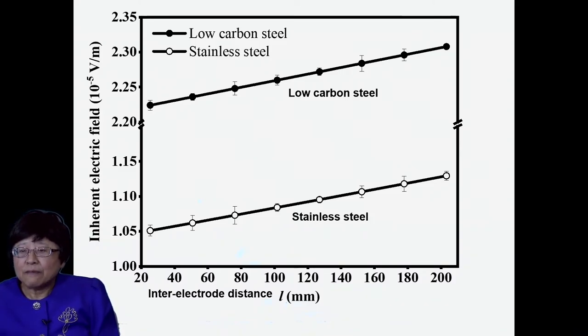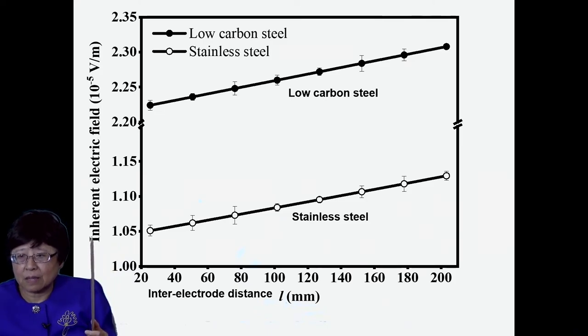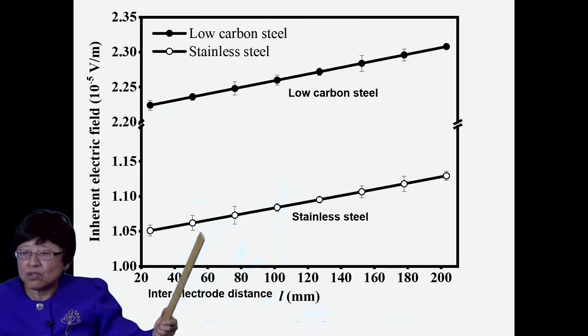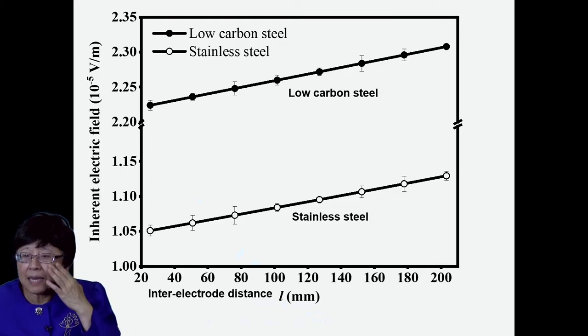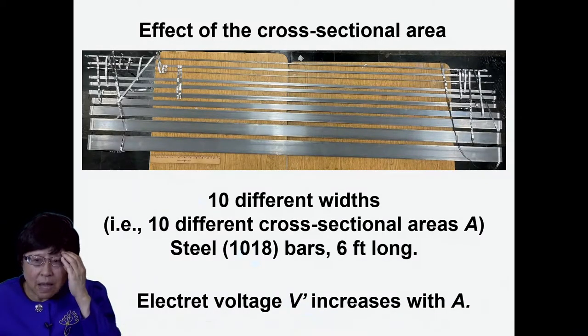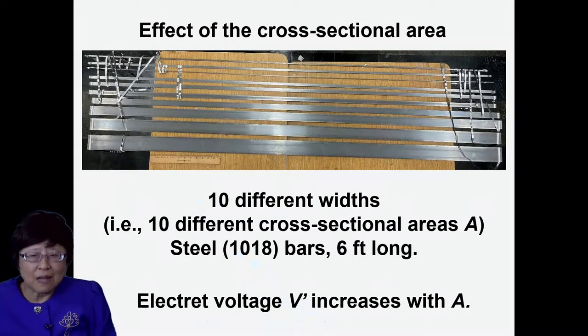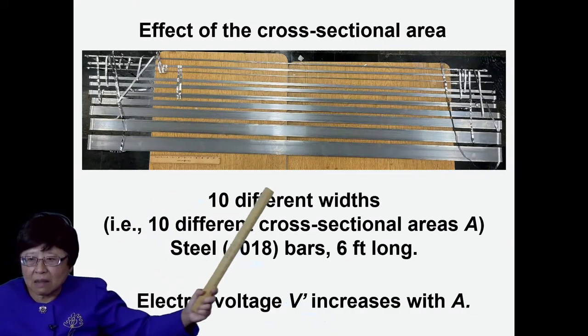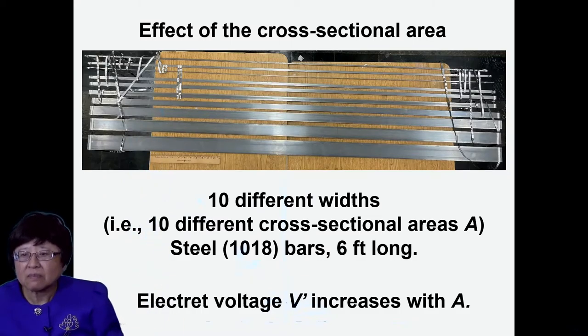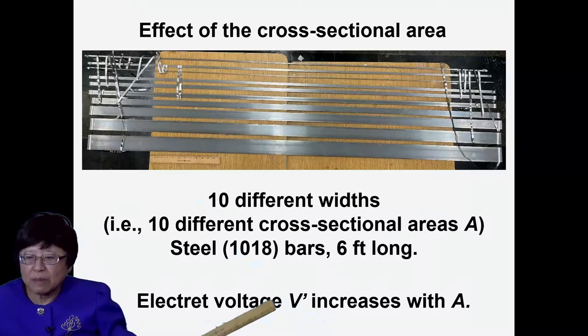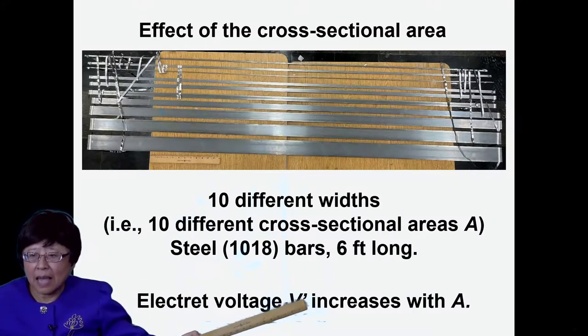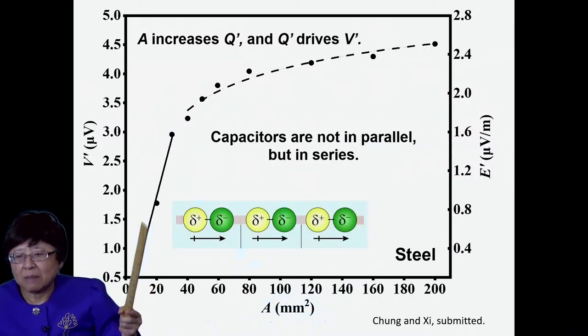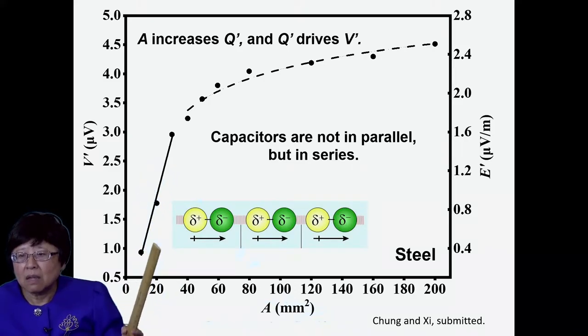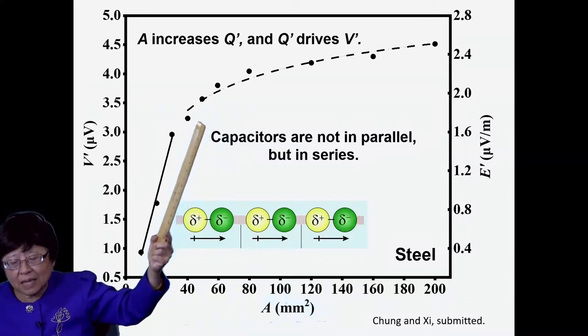This shows the effect of the inter-electrode distance on that inherent electric field, as shown for steel, low-carbon steel and stainless steel. In general, the electric field increases slightly, not a whole lot, but slightly, with increasing inter-electrode distances for these various metals and carbons. The cross-sectional area, as opposed to the inter-electrode distance, also affects the voltage or electric field. And we studied the effect of the cross-sectional area using steel of the same length, namely 6 feet long, but 10 different widths. We measured the electret voltage, which we call V prime, versus the cross-sectional area A. And we find that this voltage, V prime, increases with A linearly when A is small, but nonlinearly when A is bigger, but still keeps increasing.